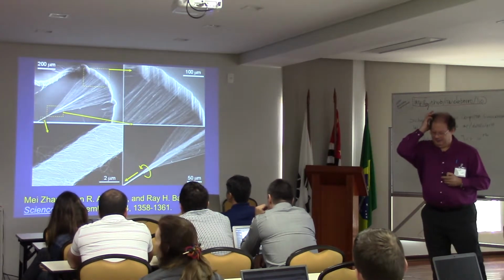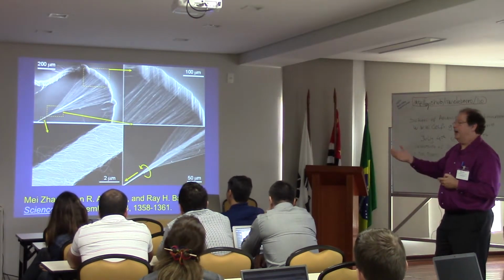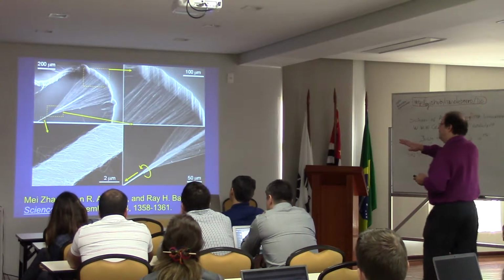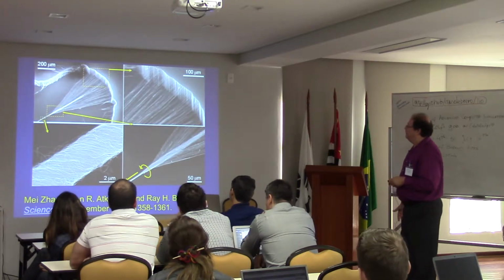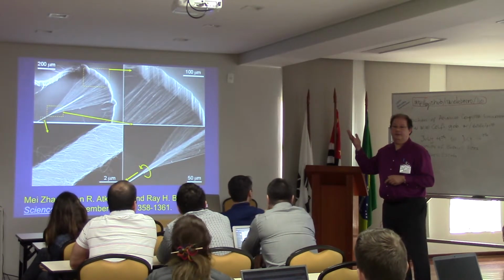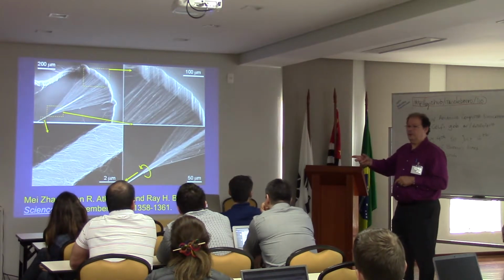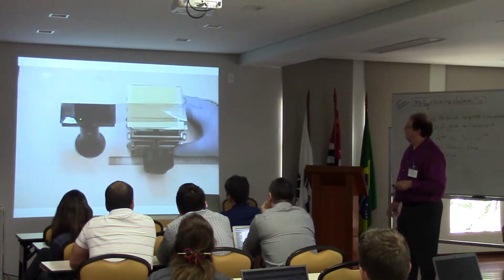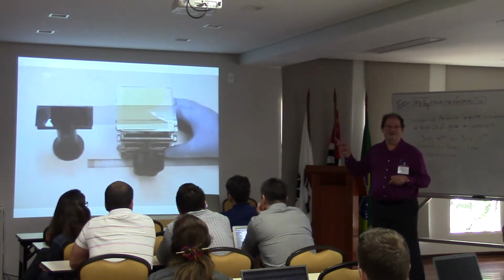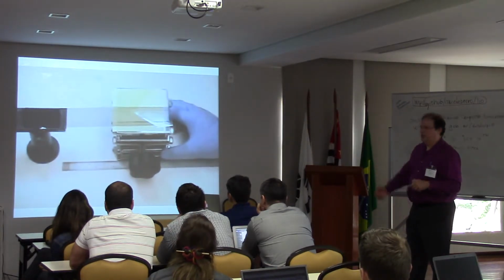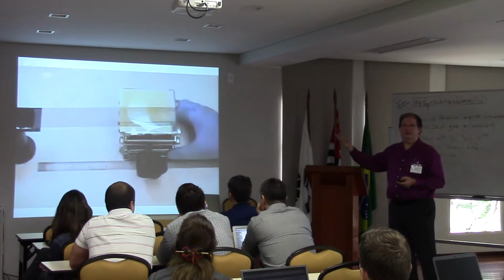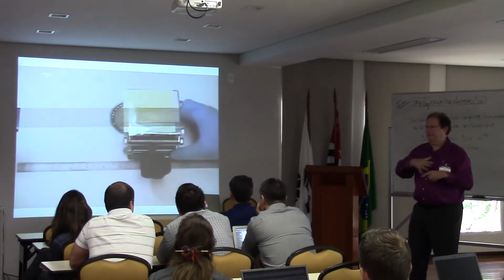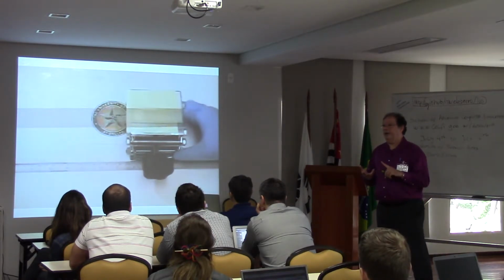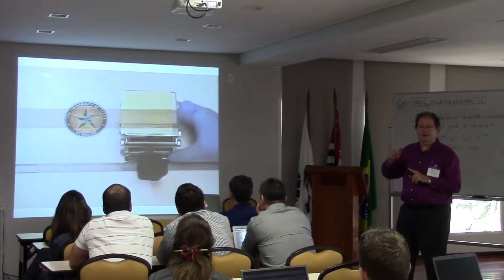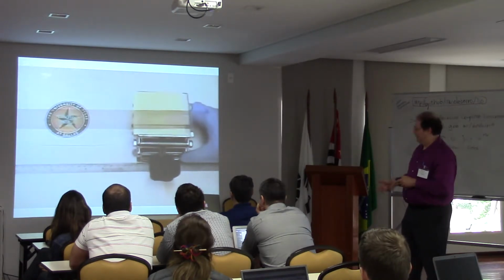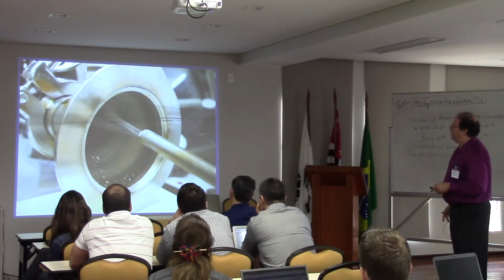But you can play with this material to produce many things. Instead of producing papers, I can produce yarns. And how you make this is almost the same. This is the forest. We can now grow very, very good quality nanotube forest, centimeter square size. And then, very simple, again, like the Chinese make silk. This is the forest, this is Scotch tape. I just pull, it comes. If I twist, I can produce the yarns. So I can produce the papers. If I mix them, I can produce the yarns, or I can produce the silk-like structure if I twist, but not very much.